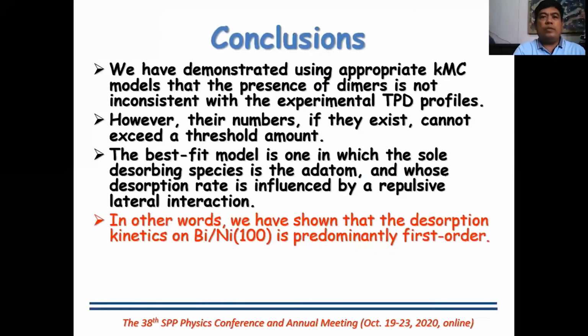To summarize, we have demonstrated using appropriate KMC models that the presence of dimers is not inconsistent with the experimental TPD profiles. Their numbers, if they exist, cannot exceed a threshold amount. The best fit model is one in which the sole desorbing species is the adatom, and whose desorption rate is influenced by a repulsive lateral interaction. In other words, we have shown that the desorption kinetics of bismuth on nickel 100 is predominantly first order.